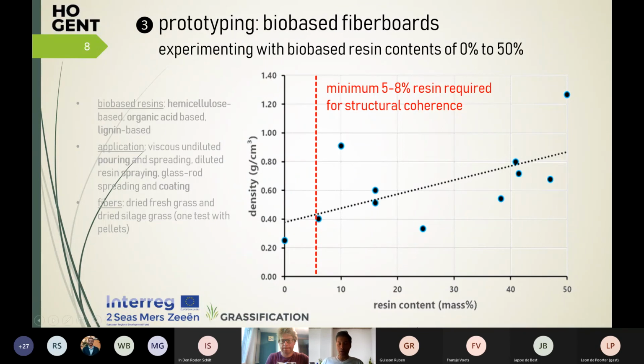Here is shown on the right a graph showing the different amounts of resin that were used, going from 0 to 50% in mass fraction, and the resulting densities going from 250 to over 1.2 grams per cubic centimeter. So we noted that with less than 5% of resin, we could not obtain a structurally bound panel. So a minimum of 5 to 8% of resin is required to obtain bonding.